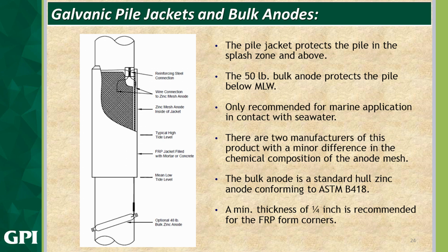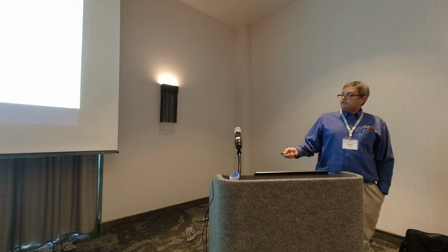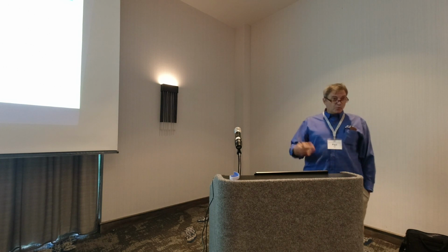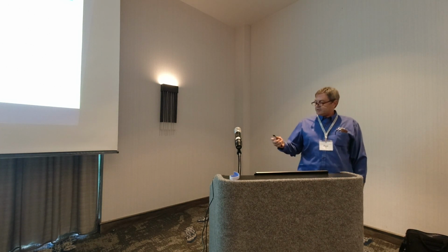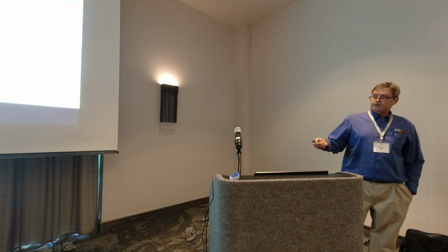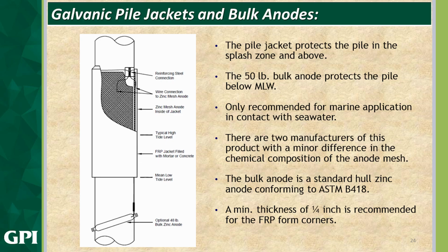The pile jacket provides the protection in the splash zone and above. So our water line would be somewhere around here. We have a 50-pound bulk anode that protects the pile below the water line. So we have two different electrolytes here. Up here, we've got concrete. The anode is directly in the concrete, and it's concrete to steel, right? That's our circuit. Down here, we've got water, and we have concrete, and then the steel.